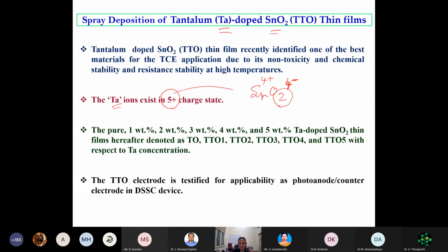When I put tantalum in a 5+ charge state, okay, when I put tantalum oxide here, what happens is tantalum will use 4 electrons to bind with oxygen, and 1 electron will be left free. This electron will be donated to the lattice, and we can improve the conductivity of tin oxide. Okay, so what we are doing in this work is we are putting different concentrations of tantalum into tin oxide, and then we are trying to see which combination is best for our transparent conducting oxide application. And then we also tested this one as a counter electrode for making a solar cell.